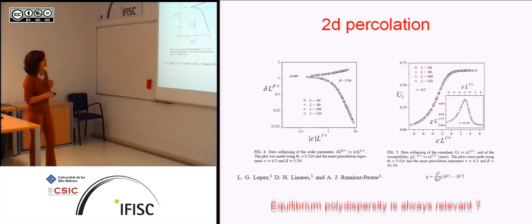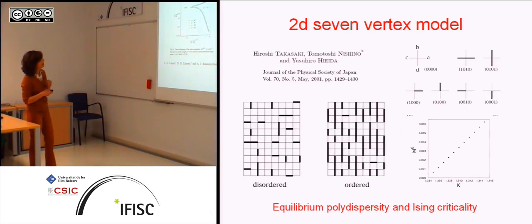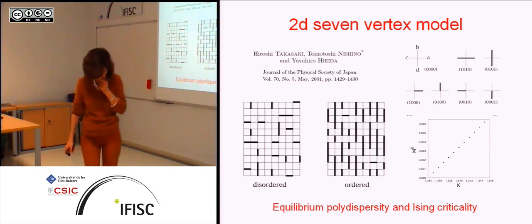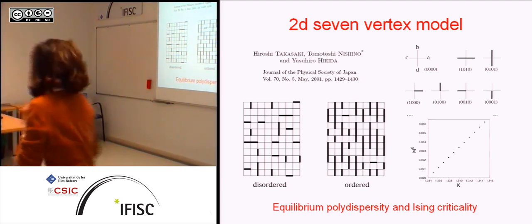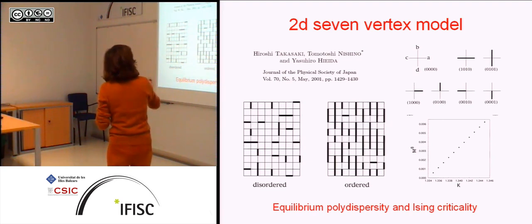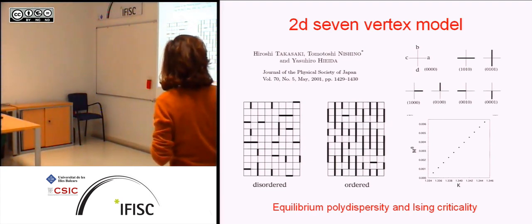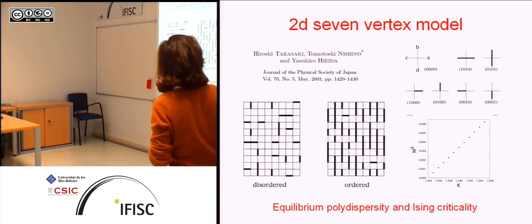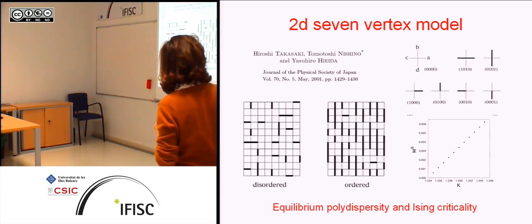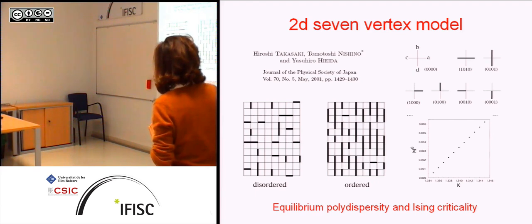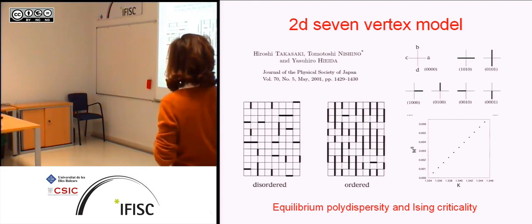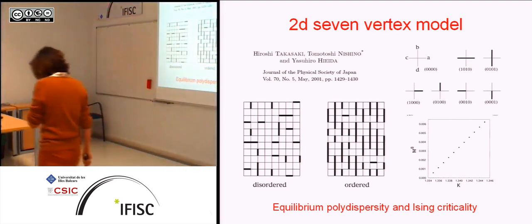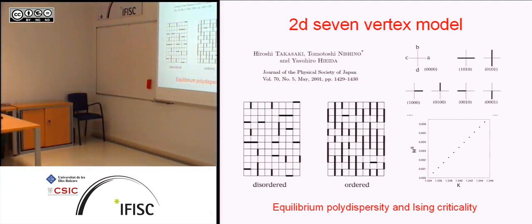And I'll say a few words about some of the things we're doing in that direction, but we didn't have to wait very long for a Japanese group that worked on very similar models, not exactly the same models. And I won't go into this, but this is one of the famous vertex models. It is the 7-vertex model, meaning that the only thing you allow are the configurations that are depicted here on this side. And so these are the sorts of things you can have on a lattice. So you have these dilute, disordered configurations, and then there is a phase transition to some ordered configurations. And these people did use a slightly different technique, density matrix renormalization group, and this is Ising criticality.